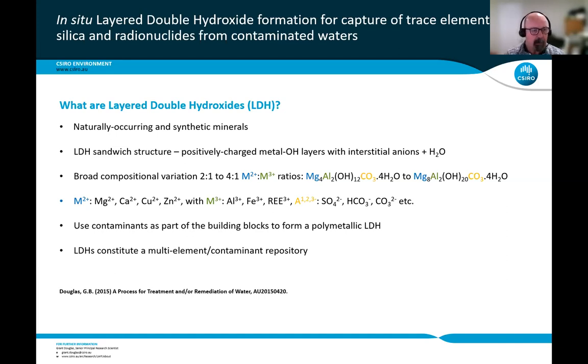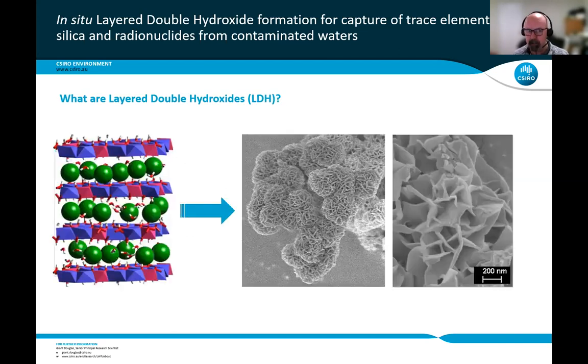And one of the really fortuitous outcomes of when you actually make in situ layered double hydroxides, as opposed to ex situ ones that you add, for instance, to a contaminated water, is that you're able to use these contaminants as a building block in the layered double hydroxide. So you can form what I've termed here polymetallic layered double hydroxide. So they can be a whole range or a whole mix of both anions and cations in the structure. And so I've said there in the last point, the layered double hydroxides then constitute a multi-element contaminant repository.